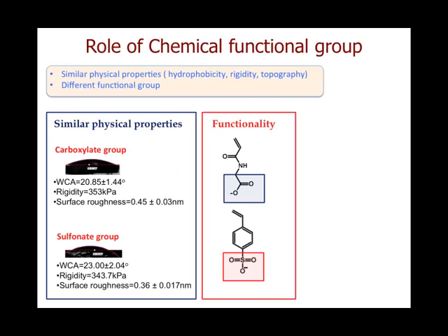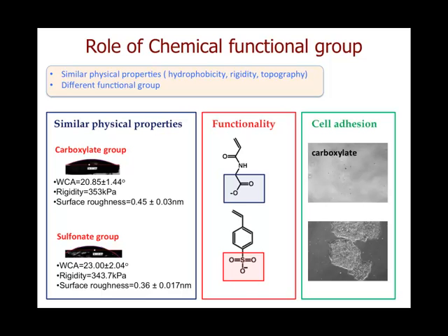We also now wanted to figure out the carboxylate group versus sulfonate group. That means you have a COOH group and you have an SO3H group, and this is one and this is another one, and we matched every property, and we know that it works only with the SO3H group. So it works only with a sulfonate group. And the beauty of heparin is that it is a sulfonate molecule. So it was intuitive, but we wanted to prove it, so we went back and re-engineered everything, or redesigned the material, and then we proved that it works through SO3H groups.